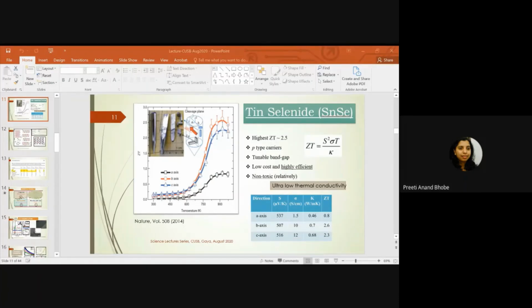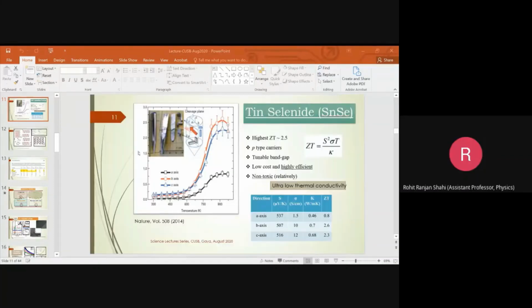Ideally, it would be better to do spark plasma sintering. If you do spark plasma sintering, then you will have a very good packing density, close to theoretical. Yeah, that's why I am asking, because for the Seebeck effect, if there is any gap, we are not able to measure accurately. Only by pressing, it is not possible to get to that densification level. No, I wouldn't agree with that, because the results I'm showing here are all hydraulic press.